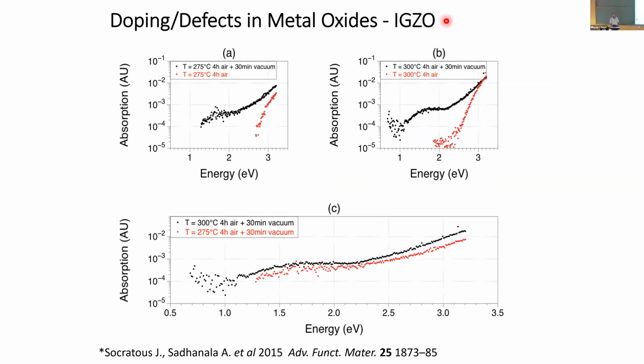Here is an example of a metal oxide, indium gallium zinc oxide. You're trying to look at the states below the band gap and see how many defects you can see within the gap. The red curve is for a sample processed in air, with oxygen present.